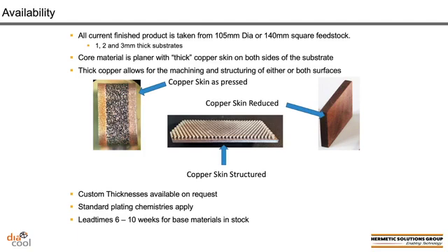has had the copper removed from both sides of the substrate, removed down as close as possible to that copper diamond matrix. And the other advantage of this process is that it allows us to add very thick skins of material to this matrix, such that we can effectively structure a surface, machine a structure into the surface of this product, as shown here in this picture in the center. In this case, this is a large substrate, roughly 6 inches long, 4 inches wide, where we have machined a pin-fin heatsink into the top surface of this part.